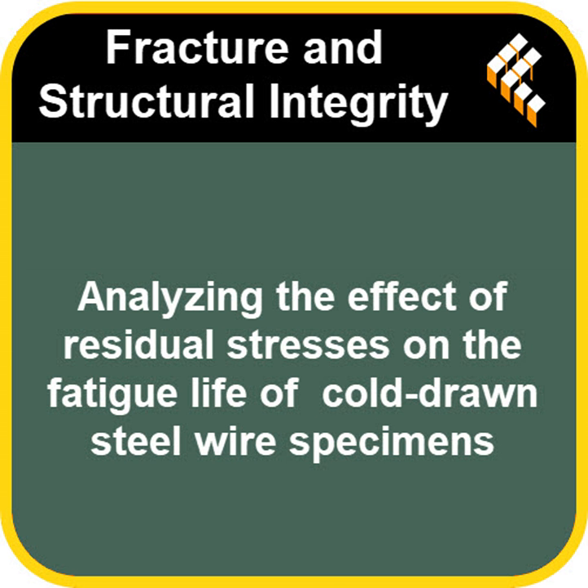benefit of the process. Even after the researchers deliberately added new, quite severe tensile residual stresses in their experiment. Exactly. Even after that phase 1 bending, the original beneficial compressive stresses from the factory were still there, still doing their job, prolonging the wire's life. That is a really powerful takeaway. It improves our fundamental understanding, doesn't it, about how residual stress affects fatigue in these kinds of wires.